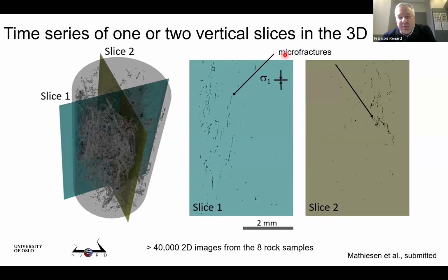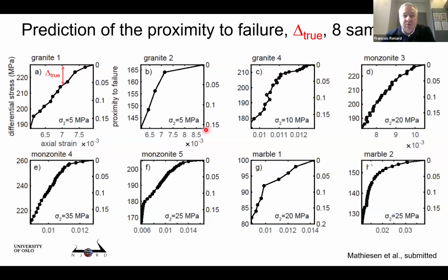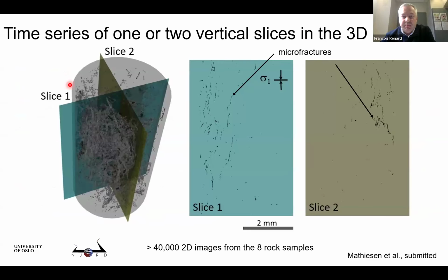As you see, this system is very sparse. We have a lot of 0s and very few 1s where there is a fracture. So the goal is to feed a deep learning model with this image and to make a model that will predict the proximity to failure. From 8 samples and several 3D scans, we produce 40,000 2D images of this kind. And for each image, we know the distance, the proximity to failure. We know this distance because we know that this 3D sample has been taken at some distance.